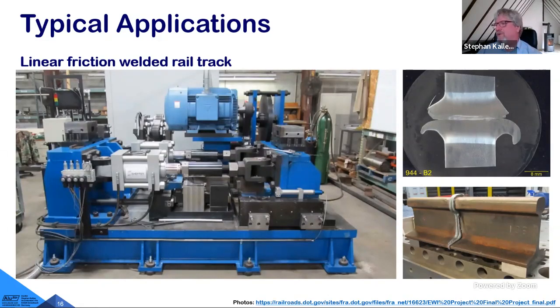A dream coming true is going on in America at our friends at Edison Welding Institute, Jerry Gould. This is, instead of using flash butt welding, which has advantages and limitations, using linear friction welding for making rails. Rails, instead of using thermite welding, either in the factory to make long welds that cannot be made in one part and then transport them onto site, endless rails to be made in the factory as shown here, but ideally even with a portable machine to be done on the construction site to join the high-speed rails. I have had a good look at this machine.